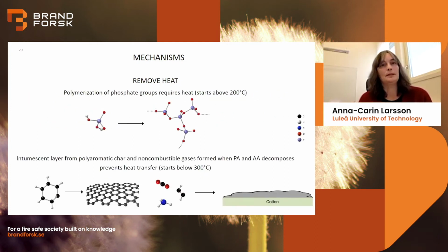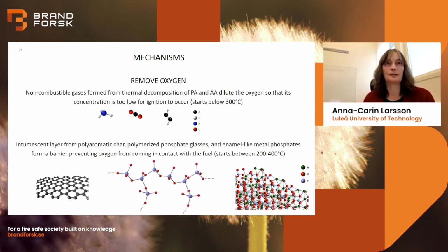Then we will remove some heat again, because those phosphate groups above 200 degrees will start to polymerize, and that requires some heat. We will also have those cyclic hydrocarbon rings from the phytic acid. They will fuse together and form this polyaromatic char. And together with the gases that also form, CO2 and ammonia, that are non-combustible, they will intumesce this charred layer. So it will start below 300 that we will get this intumescent layer as well. And this will prevent the heat transfer when it's formed.